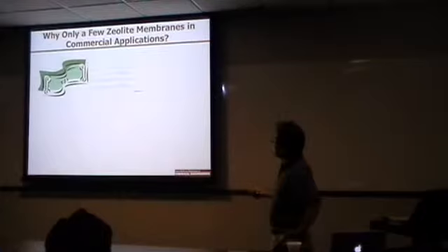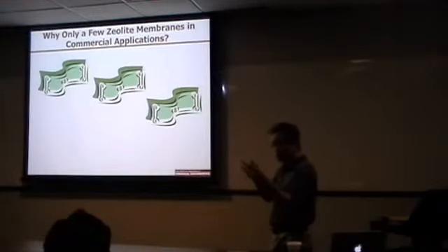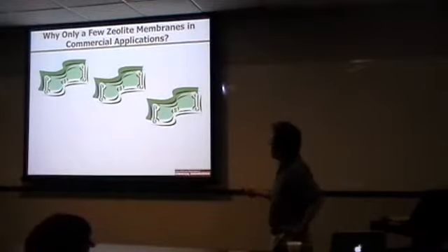on a new technique that we are developing right now. If you take a look at, say, zeolite membranes, they have been around for a long time. Zeolites are also sponges, but in zeolites we have a metal oxide sponge. The problem is basically cost. This is still $4,000 per square meter, as compared to polymer membrane, which is about $20 per square meter. The reason is because of bad process and difficulty to scale up, expensive supports, and other reasons.